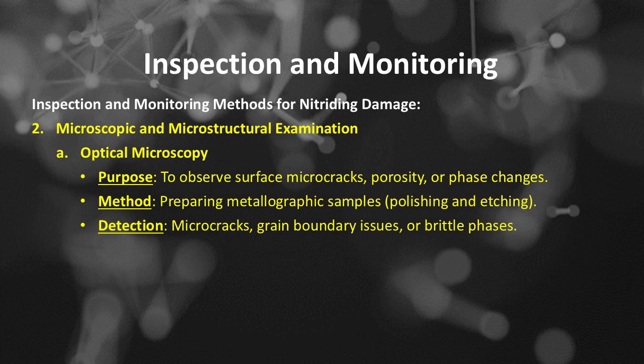Number 2 of inspection and monitoring methods for nitriding damage is microscopic and microstructural examination. Number A of it is optical microscopy. The purpose of optical microscopy is to observe surface microcracks, porosity, or phase changes. The method is preparing metallographic samples, polishing and etching. Optical microscopy is used to detect microcracks, grain boundary issues, or brittle phases.